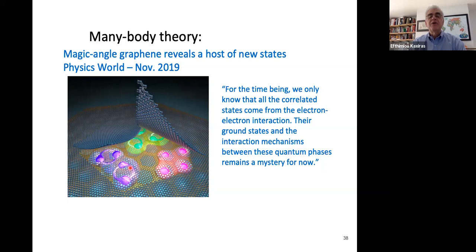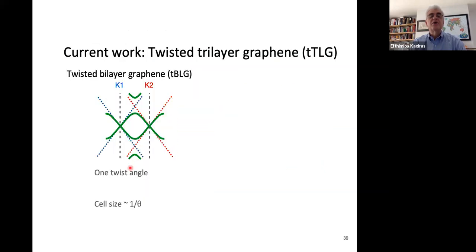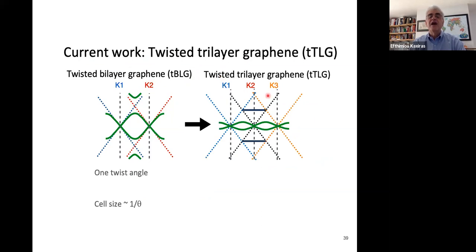Okay. So what I want to tell you for the last few minutes is a little bit about more recent work. The current work involves trying to understand the twisted tri-layer system, three layers of graphene. So here again is the schematic picture of the two layers that I mentioned earlier, the twisted bilayer graphene. Here's the twisted tri-layer graphene with an extra Dirac cone. Before we had the blue and the red Dirac cones intersecting here. Now we have the red, the blue, and one more, the black Dirac cone, all of them intersecting. So two of the intersections are here and produce the flat bands, and there's one more Dirac cone here.